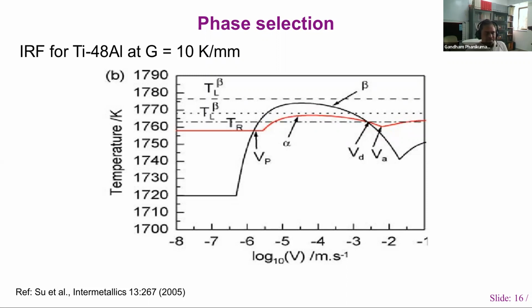Now this program to calculate this is being made ready by Hariharan as part of his PhD, and it will be used in conjunction with additive manufacturing, because in additive manufacturing, we are on the right-hand side of this particular plot. So we are on the right-hand side. So there's a phase selection that is possible here. So we can capture it to actually understand which phase is forming at what velocities. That way we can actually control the microstructure also. Particularly titanium aluminum alloys is very important, because you may want to play with it to get a specific phase to solidify upon printing.